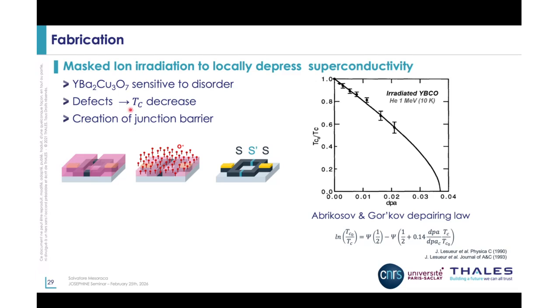So how do we make junctions with irradiation? It's all based on the principle that YBCO is a material that's very sensitive to disorder. So whenever we change the crystal structure a tiny bit or the oxygen content in this complex crystal structure, the superconducting behavior of this material changes dramatically. This was actually studied already in the early 90s because of the interest in these kinds of high-TC materials. And it was shown that the decrease of critical temperature as we increase the number of displacements per atom in the YBCO follows the Abrikosov-Gorkov depairing law that you see written here. Meaning that the increase of disorder inside the YBCO acts as a depairing mechanism, depairing meaning that the Cooper pairs will be suppressed in a more efficient way whenever we increase the defects.